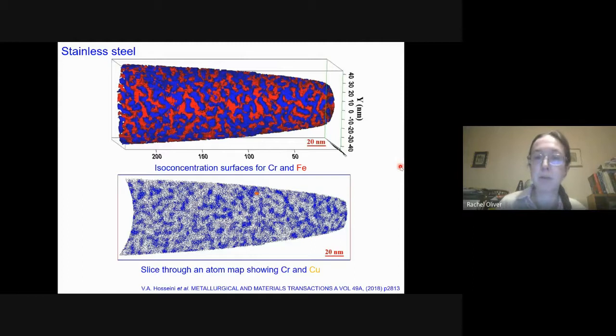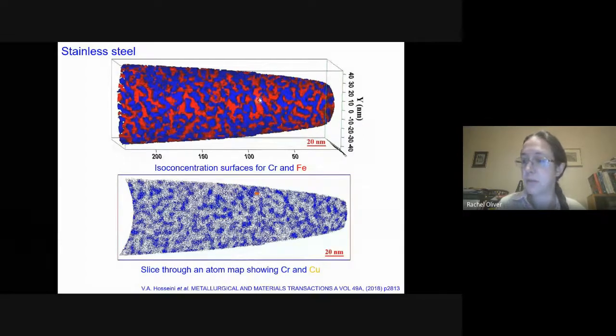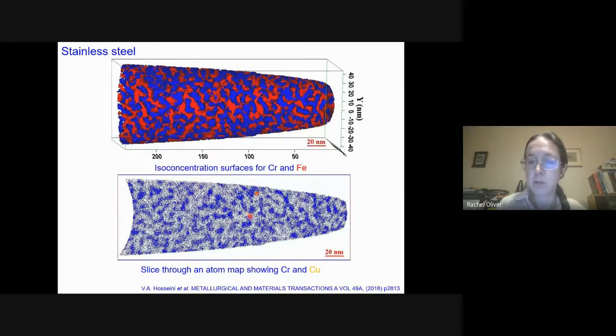Now it's animated. Right, now I'm where I want to be next. Okay. So as done on metals, you would use it to build up pictures like this. Now, this is a material that has indeed split into 2 different regions of composition, 2 different phases. It's a steel, which also contains chromium and copper. And I'm showing up this separation here as isoconcentration surfaces, which means volumes of material where the surfaces join points of constant composition. And here we're just showing up the individual atoms just as dots. We're not showing all of them, we're just showing the chromium and the copper. You can see how we can use this technique to map out in 3 dimensions. These are 3-dimensional images, and they could be 3-dimensional videos when we had the data.